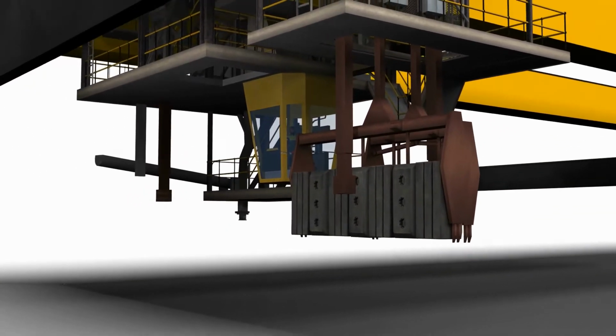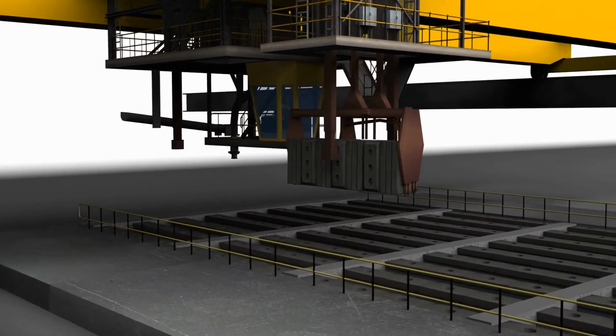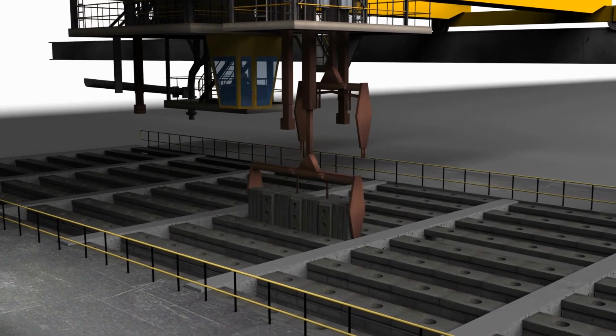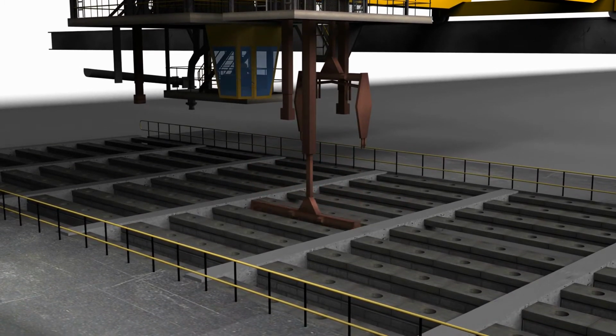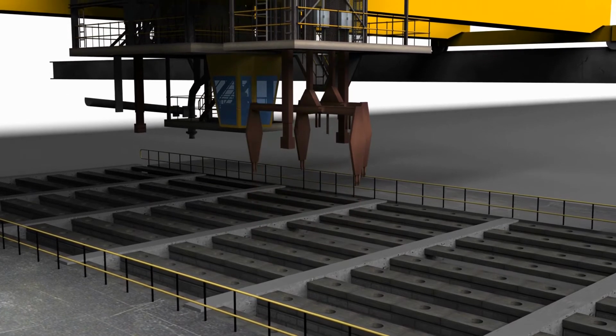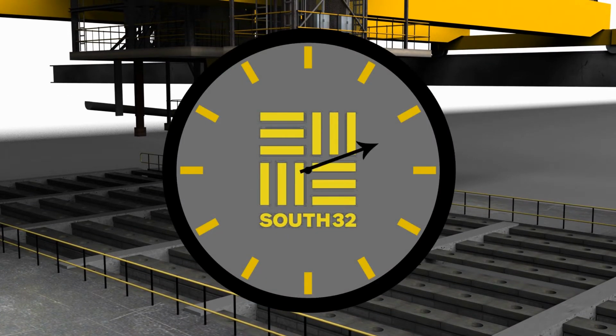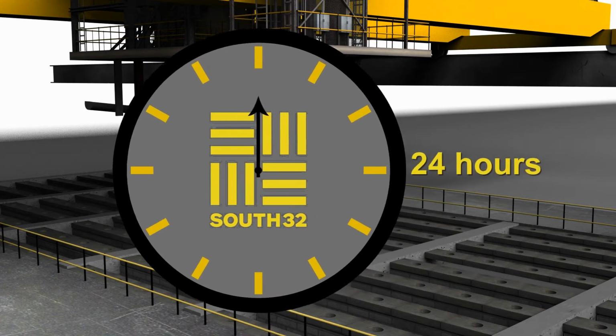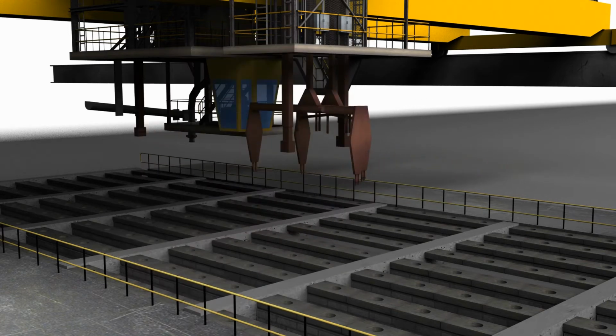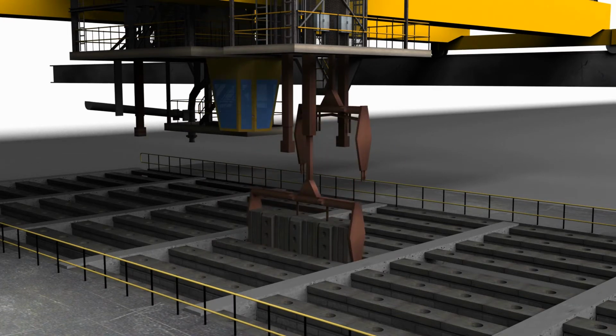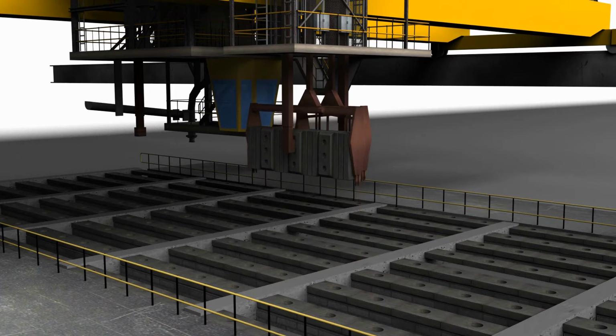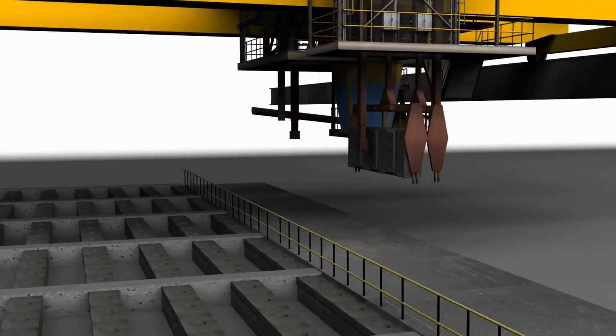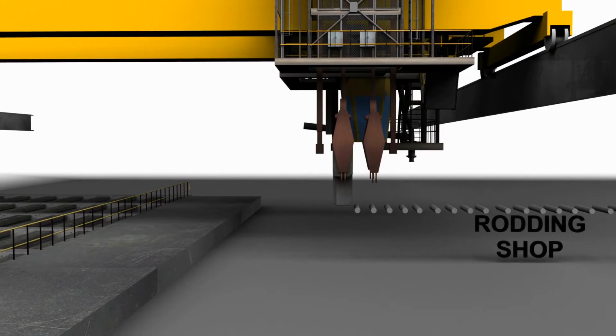Anodes are turned into a vertical position and placed 3 deep and 7 across in a gas-fired baking furnace. Baking takes approximately 20 days, gradually heating the anodes to a temperature of 1100 degrees Celsius, then cooling them slowly and evenly. Fumes from the bake furnace are treated at the Fume Treatment Center, FTC, to remove dust and other impurities, such as fluoride and tars, by absorption on alumina and by condensation.